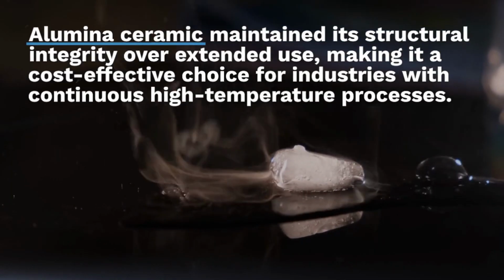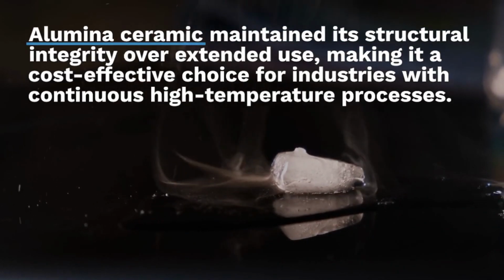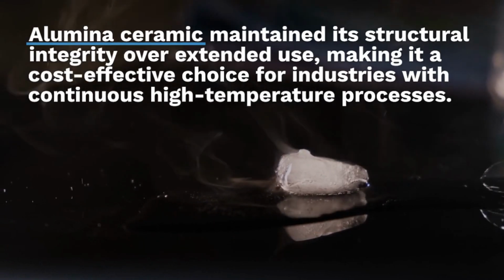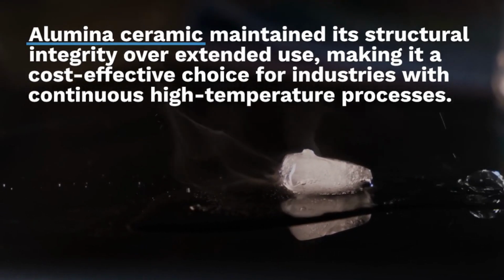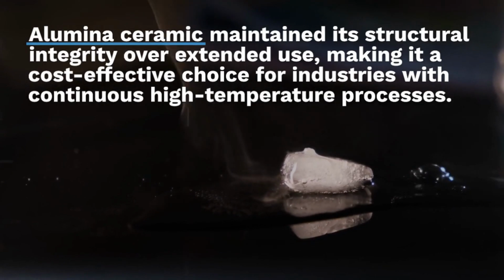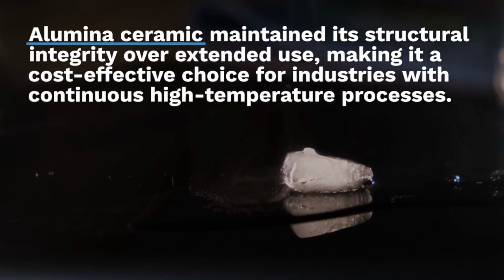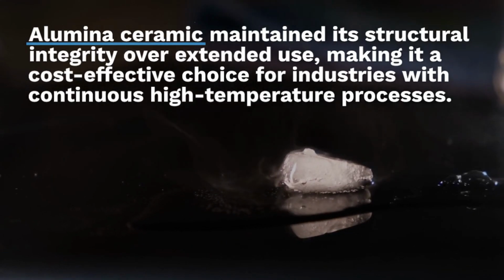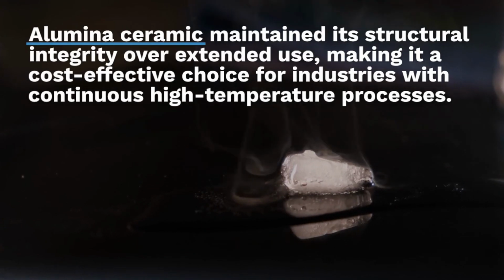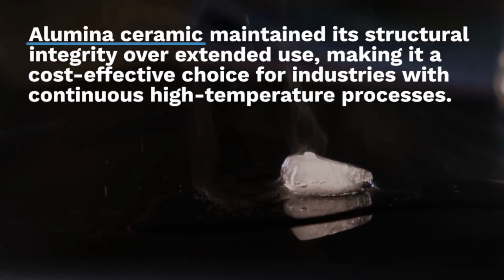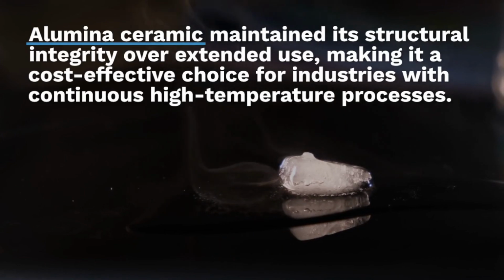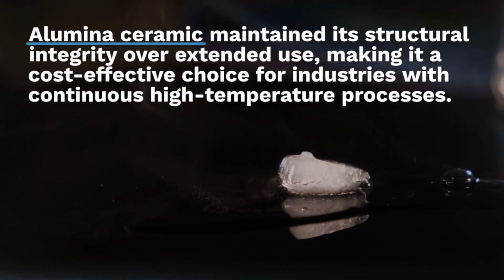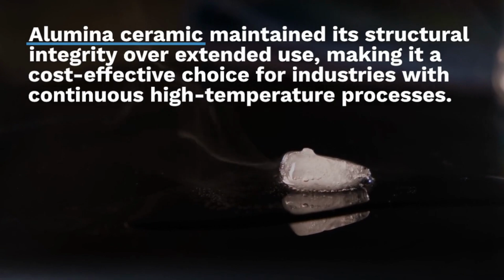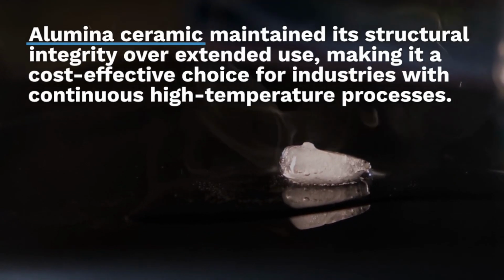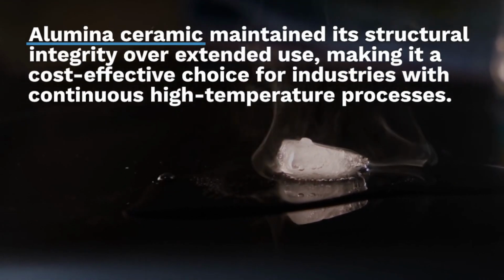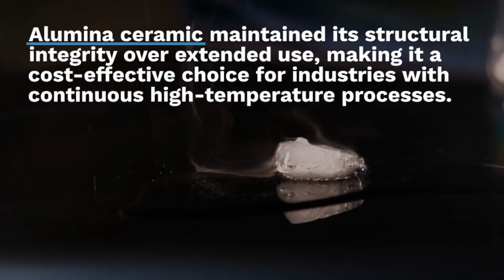To assess the long-term durability of alumina ceramic furnace tubes, a prolonged exposure test was conducted. These tubes were continuously exposed to high temperatures for an extended duration. Over time, alumina ceramic exhibited minimal wear, demonstrating its ability to maintain its structural integrity over extended use, making it a cost-effective choice for industries with continuous high-temperature processes.